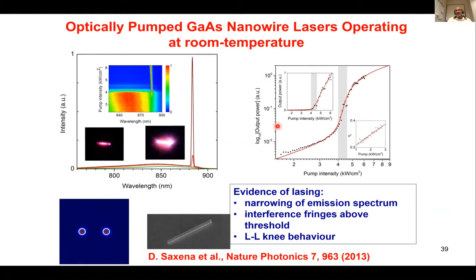You can also see the output power versus pump intensity, with the threshold-like behavior, and the log-log plot showing S-type behavior, confirming that these are really lasing. These are the first gallium arsenide nanowire lasers operating at room temperature. We reported them about 8 years back. These are also some of the smallest lasers you can think of. Just to give an idea, I can put about 20 lasers across the width of your hair. That really tells you how small they are.